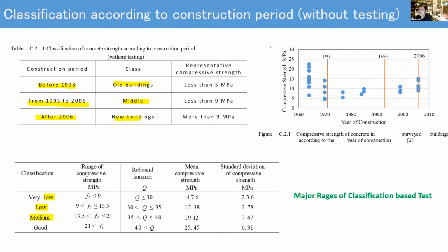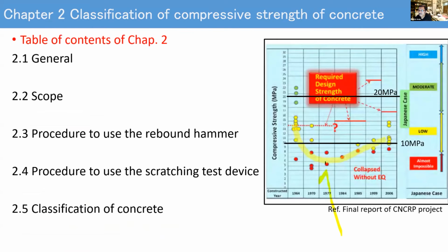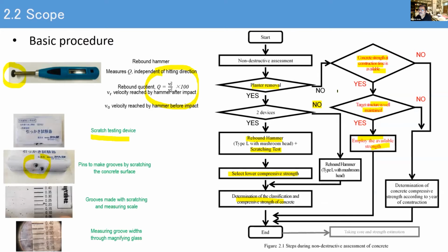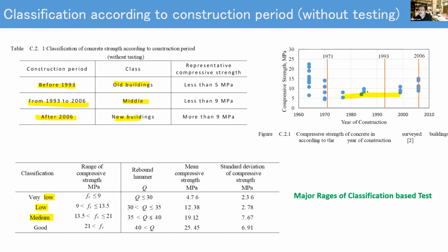In our study, which came from the CNCRP project, we replotted this figure here, and you will see the bottom mark is around 5 MPa or around 10 MPa. So we took the conservative value. If nothing is available and it is an old building, we propose 5 MPa to start with. Between 1993 and 2006, we take about 9 MPa, and after 2006, we can take more than 9 MPa. So this is our initial assumption, of course from the safe point of view. Then what if we can find something better in our test? The major range of classifications will be based on the test that I'll be presenting in the next slide.